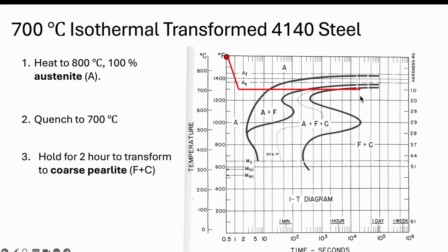And you'll notice here that we're on the upper end of the C shape. And so this takes quite a bit of time to do. And we're really close to where this reaction doesn't take place, or it takes a very long time to take place, as you can see by this curve that we have here. But we should see coarse pearlite. So again, it's got the pearlite structure, but it's got thicker and thicker bands. So this is going to be our coarsest, so we call it coarse.